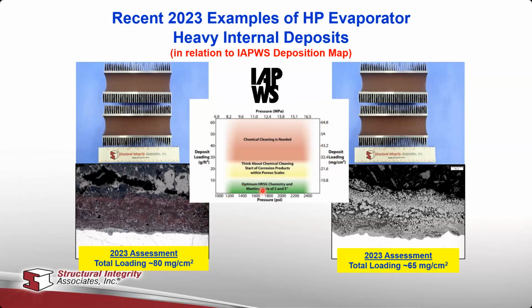And you know that if you take a sample and you measure the deposit loading and it's in the green area, then there's no possibility of you having hydrogen damage. But if, for instance, you take it in the top of the yellow or in the red, these are very heavy deposits, and that means that if you have some contaminant ingress, you can get hydrogen damage. So these are two examples. This one and this one on either side are two examples that we just looked at.